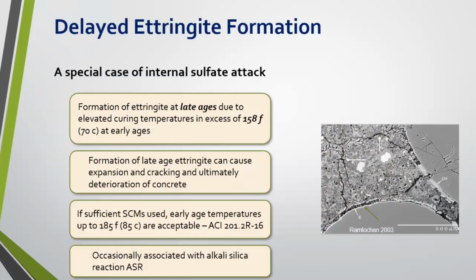So one more time on delayed ettringite formation. Again, the special case of internal sulfate attack, and with initial curing temperatures over 158 degrees. This late age ettringite can cause expansion and cracking and break down your concrete from the inside out. If you look at the photograph on the right, this microscopic view, the large gray particles there are obviously aggregates. And then in between, you're looking at the ITZ, or the interfacial transition zone. This is where your paste is tying into your aggregates there. And as you can see, where the E is at the bottom in the green arrow, you've got ettringite forming, and it's pushing against that paste off of the aggregates, kind of creating volume in that space. And as you can see, the cracking already taking place, breaking that concrete down from the inside out.